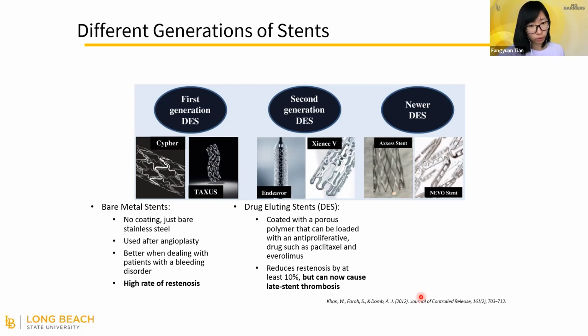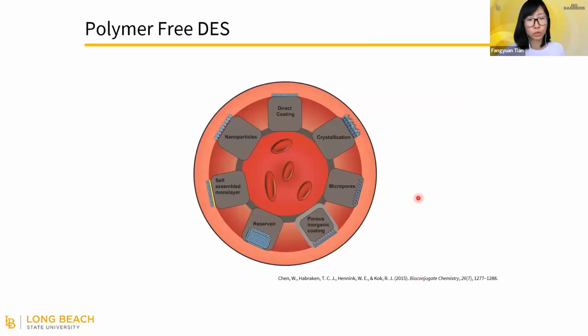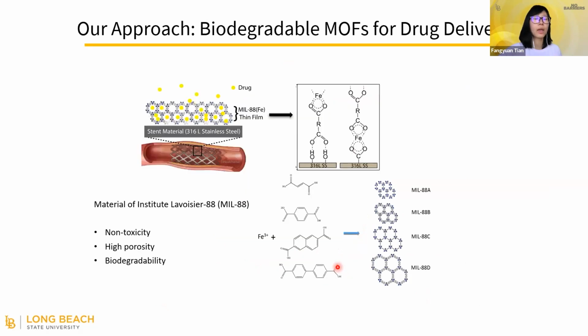So the newer version of drug-eluting stent will be made with a polymer-free material. There are many different ways of doing that, including nanoparticles, self-assembled monolayer, or direct coating. But our lab is specifically focusing on inorganic coating, and we utilize an iron-containing metal organic framework. The metal organic framework is made of iron clusters connected by different organic linkers.